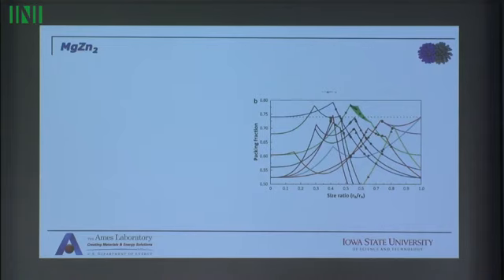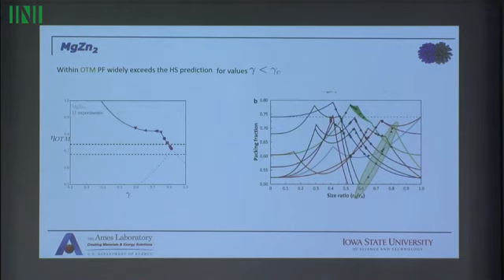Then we can also go and calculate what is the packing fraction. Now, because we have this ability to form vortices, this is the hard-sphere packing fraction, and now we develop this new branch where the packing fraction becomes higher than the hard-sphere one, and therefore we have a prediction for what would be the packing fraction if it is measured in an actual experiment. So what we see here is that all these very low packing fraction things that would be predicted if things were hard spheres are replaced by these other ones that are possible because there are vortices that allow this higher packing fraction and closer approximation.